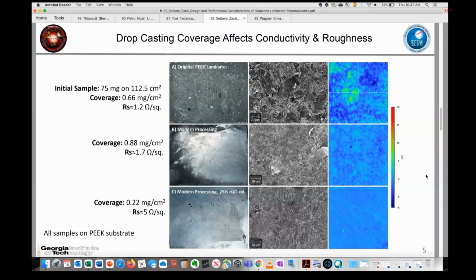And what you're seeing here is differences in coverage, and then also the bottom depicts a different processing arrangement that we can use to get better substrates that are more smooth and uniform. And in general, all the sheet resistance properties are pretty good. But as you can see, we can get down to 0.2 milligrams per centimeter squared. And we can spray coat these things, so this is something that we could apply to something like the spacecraft. I'll add that the roughness that you're seeing over here on the right progresses from being the texture of the graphene, and then eventually what we're seeing is the lines registering from the mold surface that we use to cast these samples. And this is about a 1 millimeter by 1 millimeter area. Next slide.